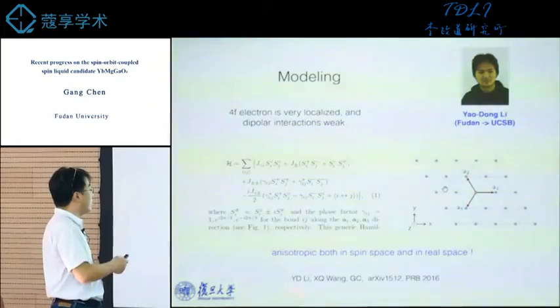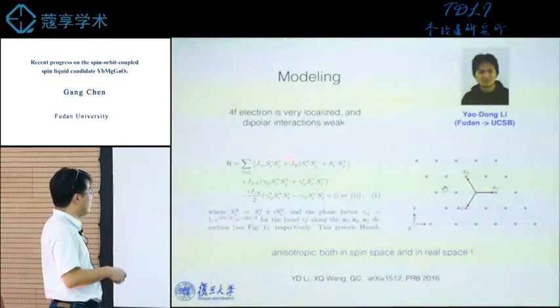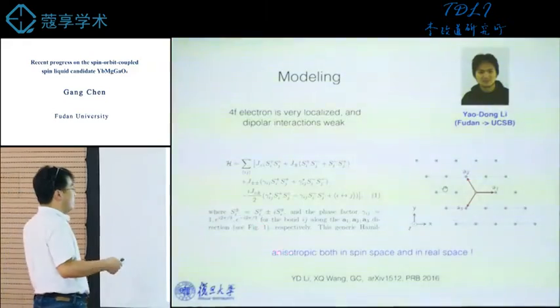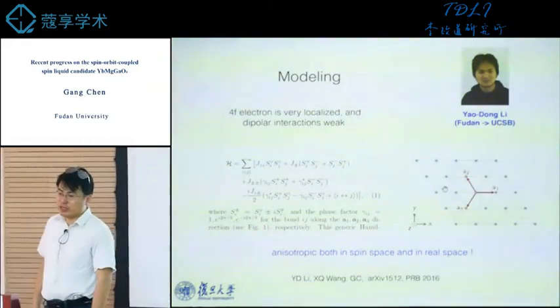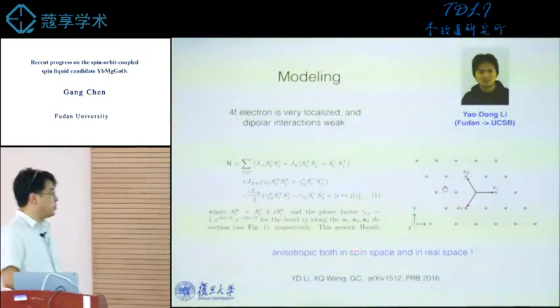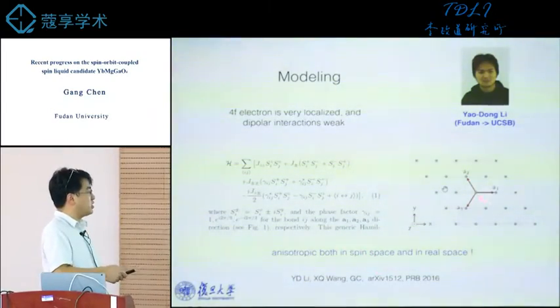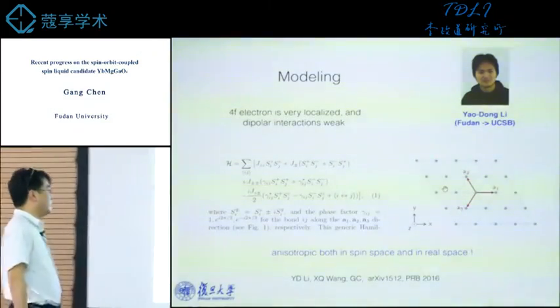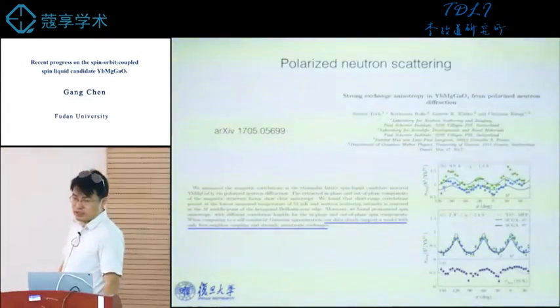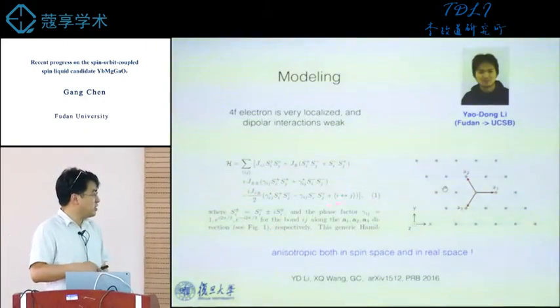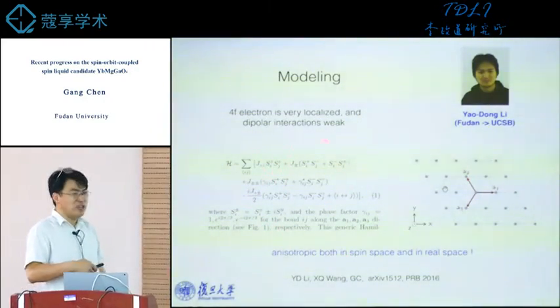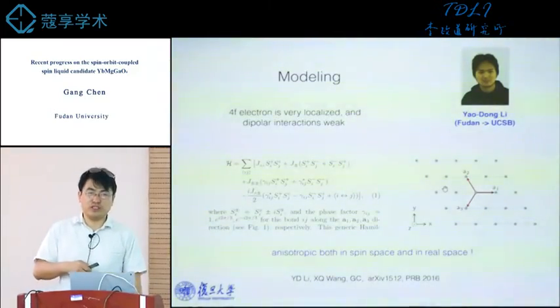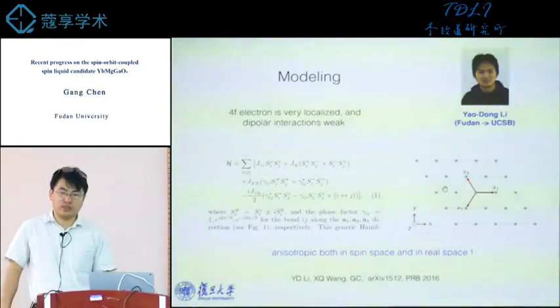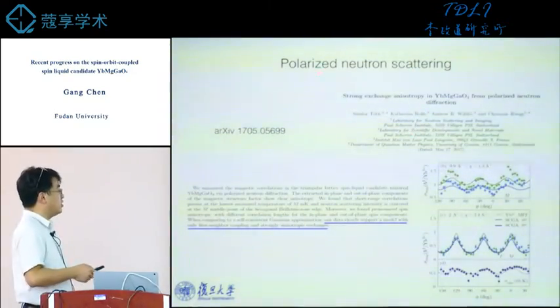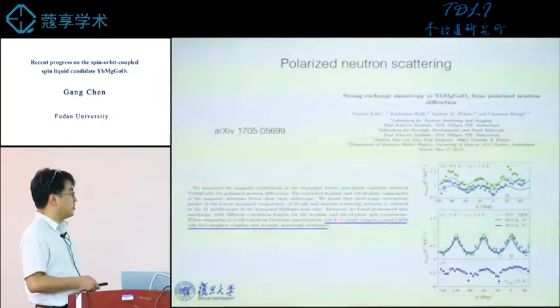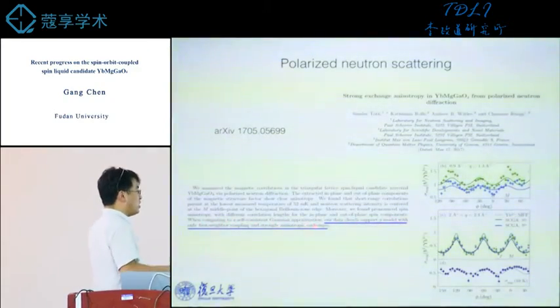My student and I carried out this modeling. It's a complex model, describing a Kramers doublet on a triangular lattice. This model is anisotropic both in spin space and in position space, so the interaction depends on the bond orientations. If you do a polarized neutron scattering measurement, the correlation function for different spin components can be different due to this anisotropy. So people actually carried out polarized neutron scattering measurements, and their data clearly support a model with first neighbor and strongly anisotropic exchange.